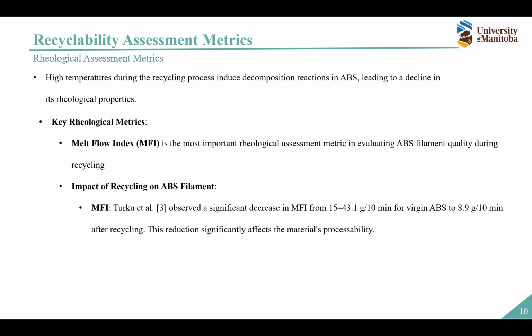Same for rheological assessment metrics. Recycling will also affect the rheological properties. We quantify this degradation by measuring the melt flow index. The melt flow index, or MFI, is the most important rheological assessment metric, which helps us to assess the recyclability of ABS. For example, Turku observed a significant decrease in MFI before recycling and after.